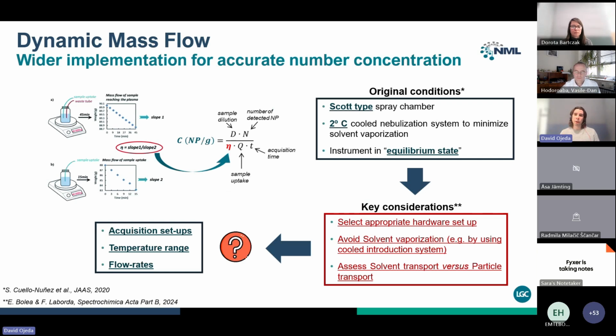These conditions were the use of a Scott type spray chamber. The temperature of the spray chamber was controlled to 2 degrees to minimize solvent vaporization, and the instrument was used in an equilibrium state. So considering these original conditions, there are some key considerations we need to take into account, such as that this was specifically for a specific hardware setup.